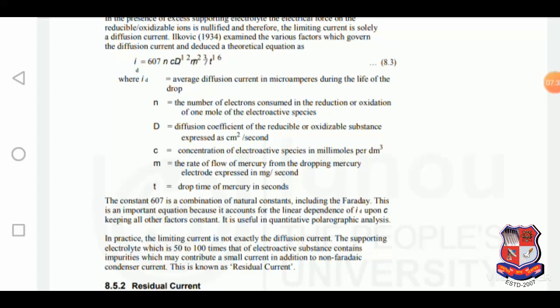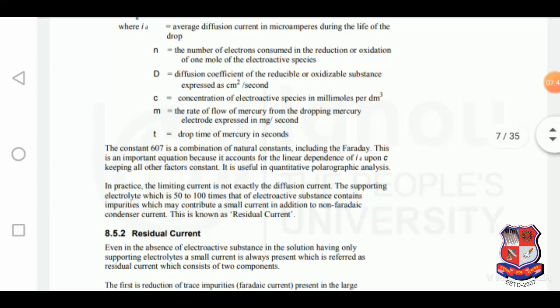This is the Ilkovic equation which is frequently asked in GTU examinations for explanation. The constant 607 is a combination of natural constants including the Faraday. This is an important equation because it accounts for the linear dependence of diffusion current upon small c, that is the concentration of active species in millimoles per decimeter cube, keeping all other factors constant. It is useful in quantitative polarographic analysis.